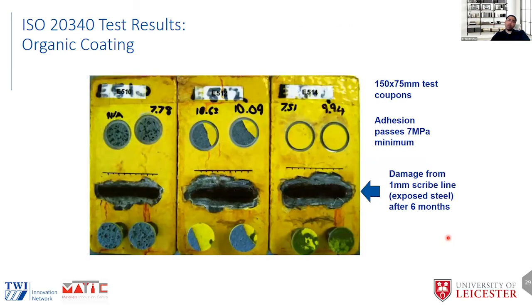And what we saw in the painted system, the circles here, these are due to the adhesion test dollies. And the numbers, 7, 10 megapascals, these are the adhesion values that we obtained from the test. And these are the test dollies you can see here. When we looked at the samples in a bit more detail, in the damaged region we saw the 1 millimeter scribe line was exposed. This was exposed steel, and we can see some rust formation, which is not surprising at all, because these coatings act as barrier layers, and if there is a breach, then corrosion is very likely.